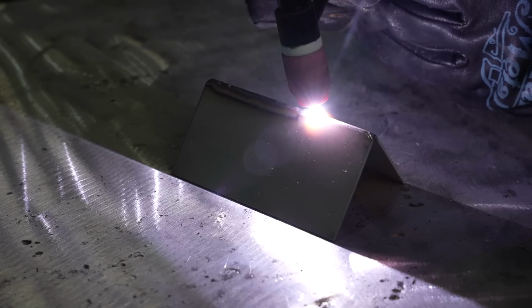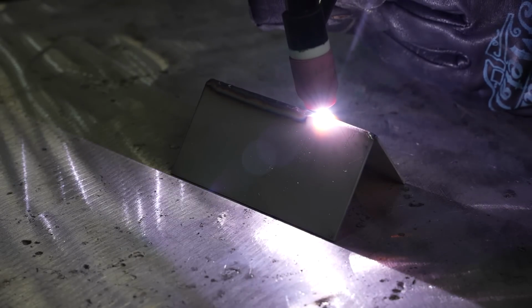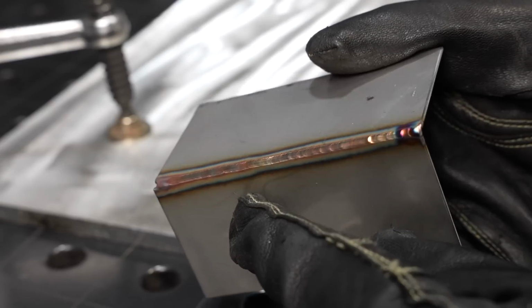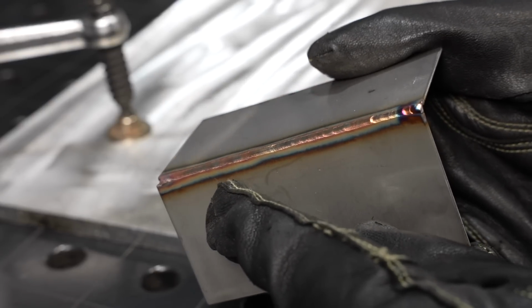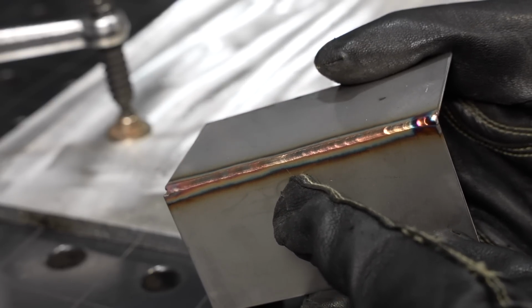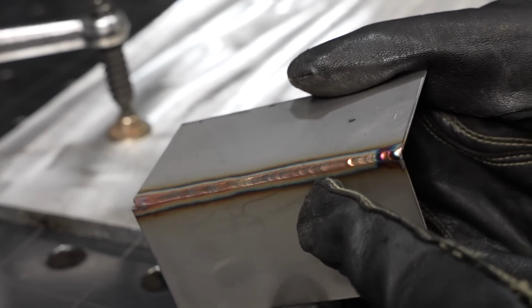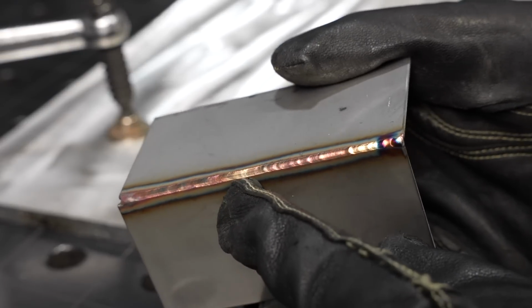So you can see here where I'm tracing along my puddle, I can control that penetration a little bit with my amperage and travel speed, and how much penetration you need really depends on the application of what you're doing. Sometimes you just need it to seal, and sometimes you want to penetrate down in deep. But either way, you can see from a shielding perspective, as I pass that cup, I do get a little bit of oxidation on the surface there, but the color is acceptable for most things and it'll hold.